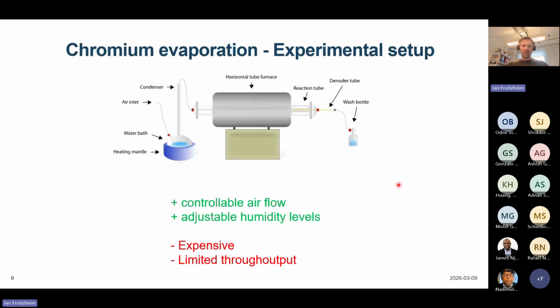So here's the schematic of our furnace system. As you've seen on the image before, it's basically almost all tube furnaces. So the furnaces here, the samples would be here in the middle somewhere. We have gas inlet here, which is humidified if we want humidity. And we actually humidify it a little bit more than we need. And we have a condenser here to condense out surplus humidity. And then it goes into the system.